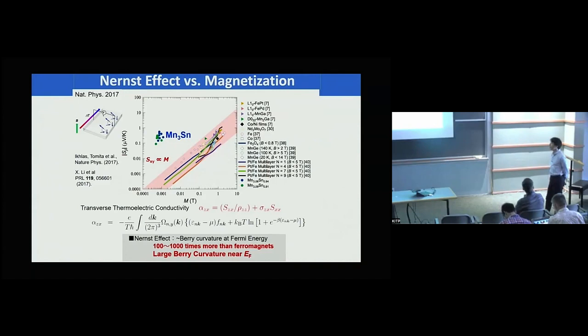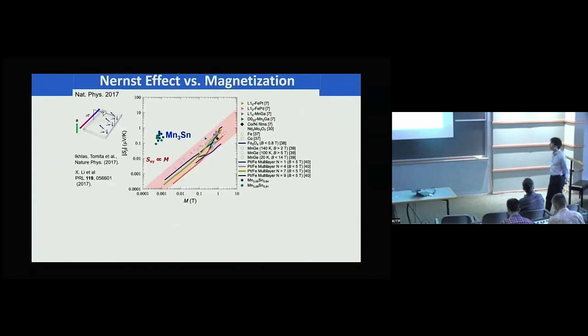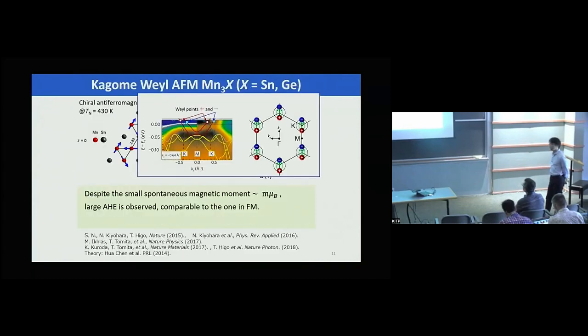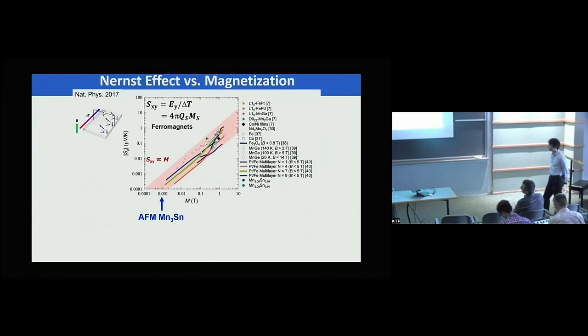I mean, if the Weyl nodes actually form a ferroic type of arrangement like this, I think you should be able to see a very large response. And we actually did Fermi energy tuning dependence of the Nernst effect, for example, and compared the result with theoretical investigation. Of course, you need to take into account U, which we need to pay attention to. But this Nernst effect, for example, one can tune the size as a function of Fermi energy and see whether it matches with the existence of the Weyl nodes, and it does.